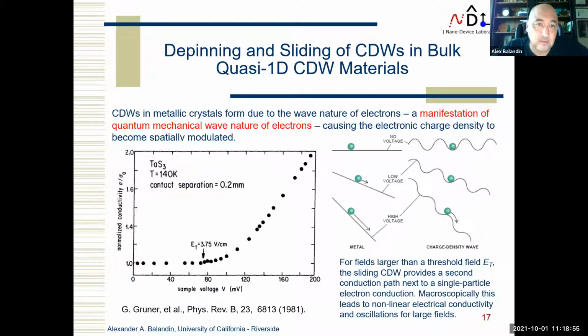So what were typical manifestations of the effects in these materials? The classical work: charge density wave was a popular topic in the 70s, 80s, 90s. What I'm showing here is that you take a material which has this transition, in this case tantalum trisulfide, you cool it down, and it enters a charge density wave regime. And by the way, because the wavelength of the charge density wave is defined by the Fermi level, it doesn't need to be commensurate all the time with the crystal lattice. If you have an incommensurate state, the charge density wave can slide. However, typically in any realistic material, you have defects and boundaries of the sample, so this charge density wave is pinned by defects, so it's not sliding.